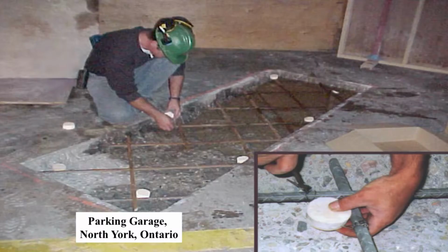Because that's going to allow the current to go from this galvanic anode here, not only to this surrounding steel, but it'll travel down these bars as well and protect the steel up here as well. Pretty simple to test for. You get a multimeter, you can put it on ohms or millivolts, and you just want to see 1 ohm of resistance or less, or 1 millivolt or less, and you know you have a good connection. If these bars weren't touching for whatever reason, there was a space, whatever, you could take a rebar tie or something like that, tie them around, make them electrically continuous, and move forward.